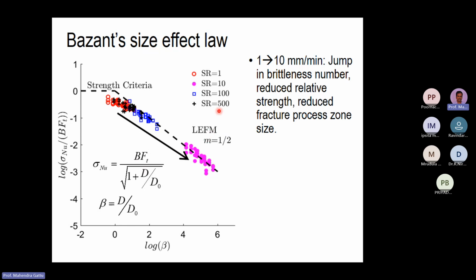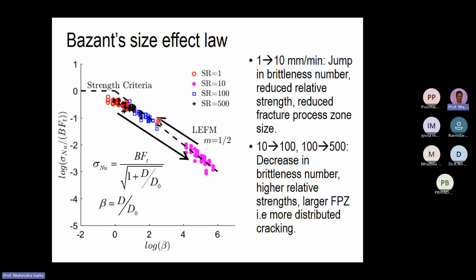And again, as we increase the loading rate from 10 to 100 and 100 to 500, these experimental data points move again along the curve towards the strength criteria. So we are moving towards the strength criteria now. So 10 to 100 and 100 to 500. So at that point of time, we thought that this was due to some loading rate effects, but right now I'm thinking that there could be viscoelastic effect, which we have not studied at that point. We didn't study in detail there. So now I'm looking into that aspect.